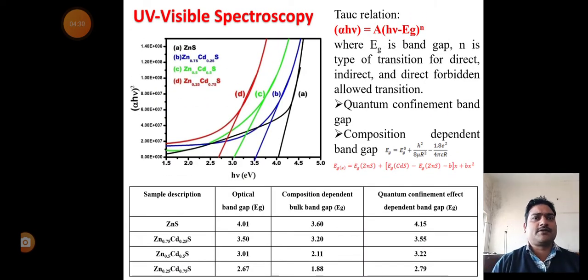UV visible spectroscopy shows decreasing band gap of the zinc cadmium sulfide as the cadmium concentration increases. The optical band gap, compositional dependent band gap, and quantum confinement effect dependent band gap are shown in this table.